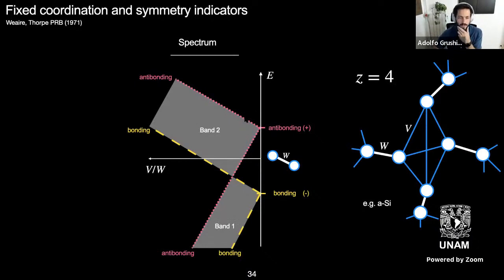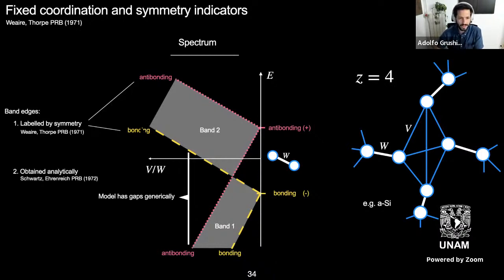And what's interesting is that what Weaire-Thorpe showed is that if you look at the envelopes of these bands, what we call the band edges, so these 2 dashed lines in yellow and pink, they're actually labeled by symmetry. So they keep their eigenstates, they're still symmetric with respect to inverting these 2 sites. And so if I pick a random state in one of these 2 bands, it would not have any symmetry. But it turns out these band edges that are colored here still have well-defined bonding and anti-bonding character. And I told you that we need to know what the filled eigenvalues of bonding and anti-bonding are, or how these states transform under certain symmetries, to know if they're topological. And so to know which states are filled, I have to know where the gaps are.